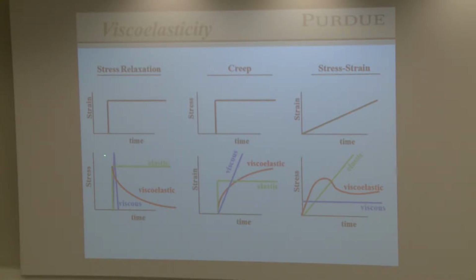It will come up like this, and then it will relax with time. So that's a viscoelastic material. It's somewhere between an elastic and a viscous material. And the key issue is things happen with time. Notice with an elastic material, there's no time dependence. With a viscous material, again, everything happens right during that step change. No time dependence. The key issue is a viscoelastic material has inherent time dependence. And polymers turn out to be viscoelastic materials.